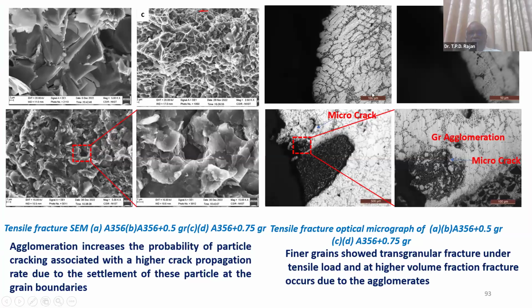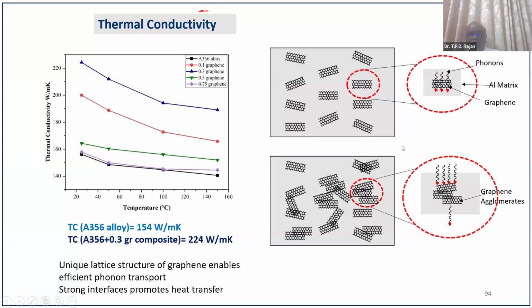And if you have a higher concentration of the graphene, what happens? The graphene gets agglomerated, and this is the region where it fails, the microcracks. But if you have a proper dispersion, then you can see throughout the area it is completely dispersed. And the thermal conductivity is also getting increased. This is at almost 25 degrees, at room temperature. By proper dispersion, you can get almost 224 watts per meter Kelvin thermal conductivity.